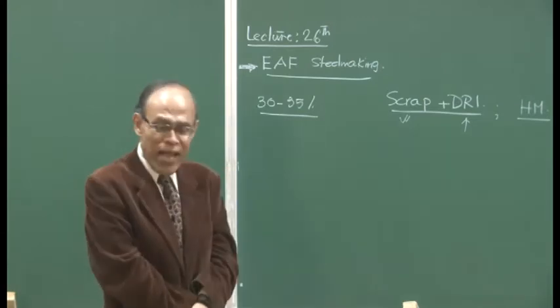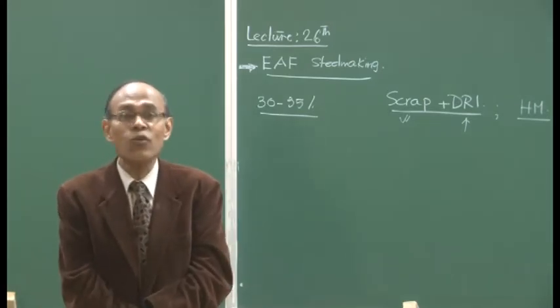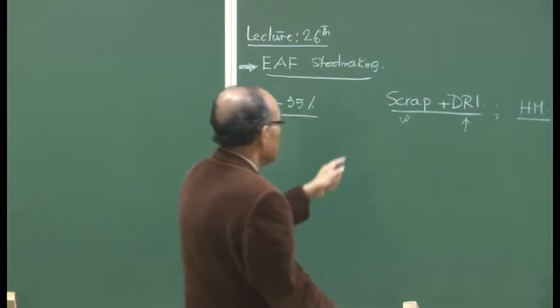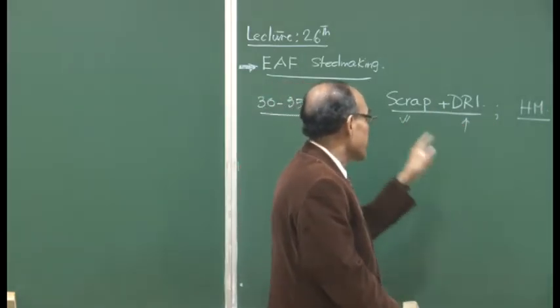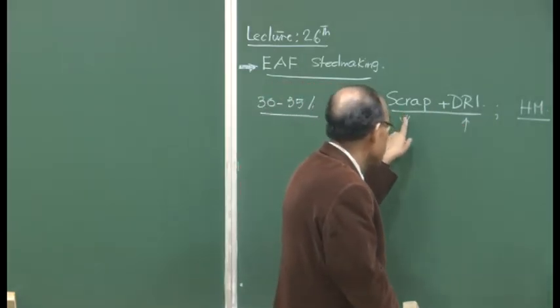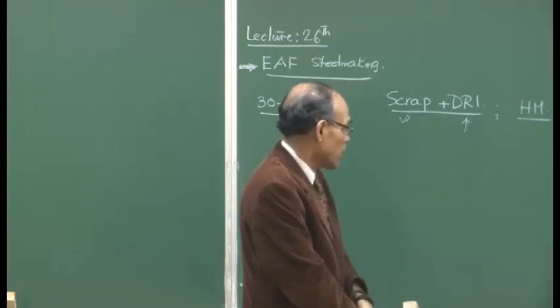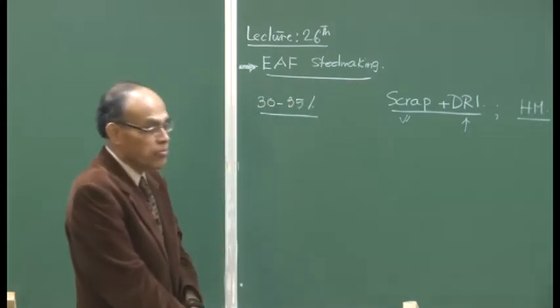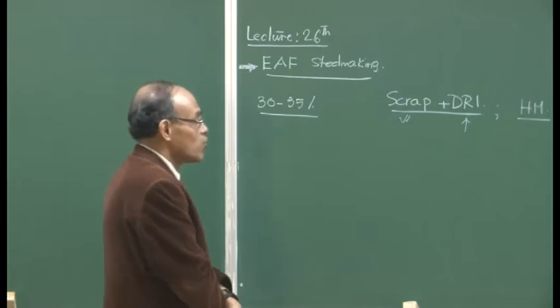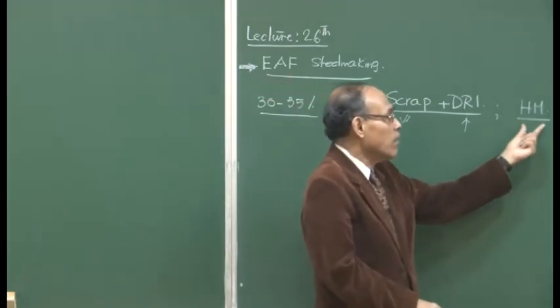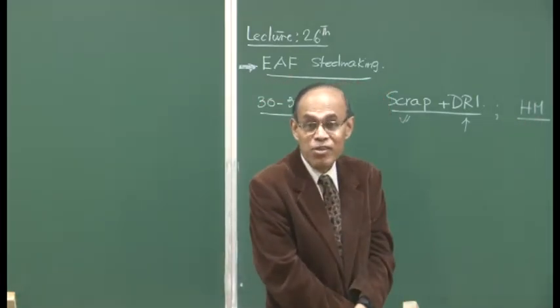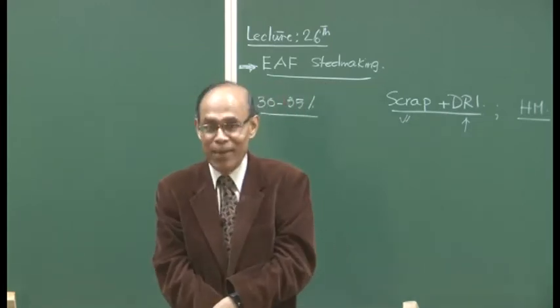electric arc furnace. So, today's electric arc furnaces mostly will be operated with feed material containing partly scrap, partly DRI and partly hot metal. And the advantage of using hot metal, as you can see, is that hot metal contains carbon, silicon, etc. So, additional heat is liberated.